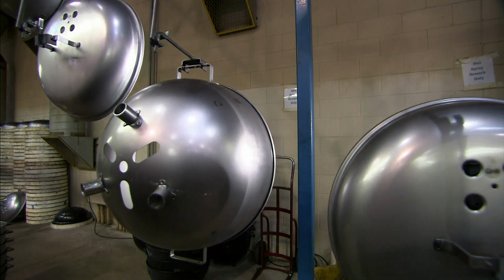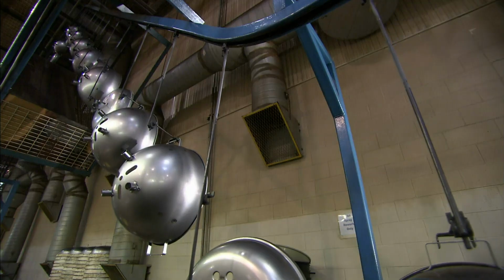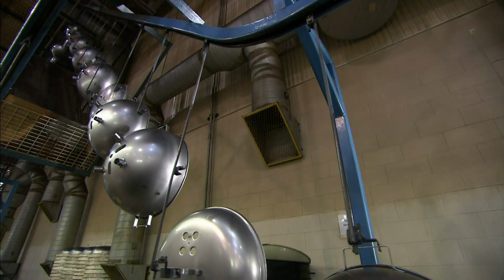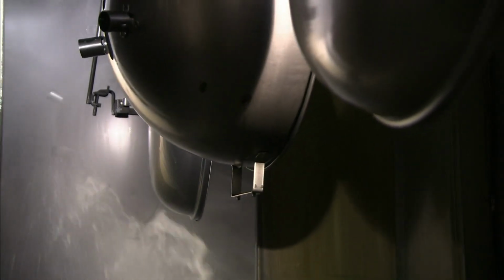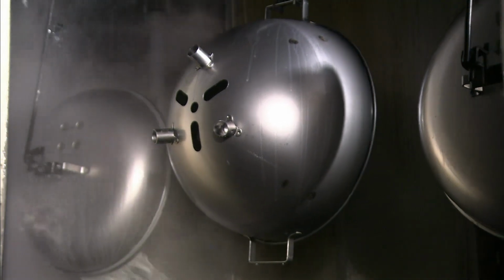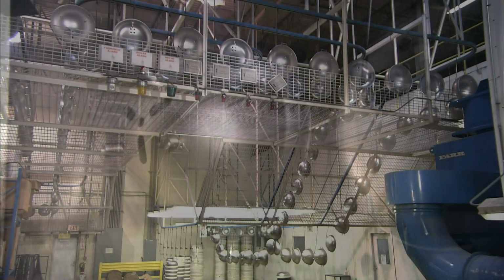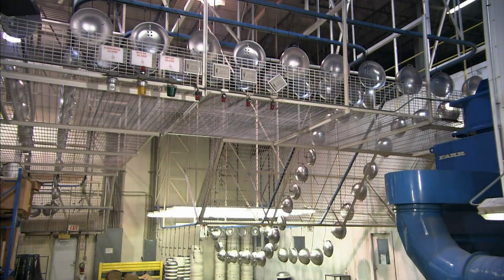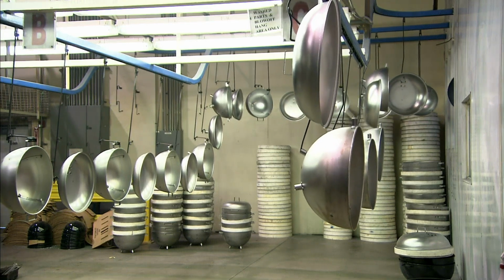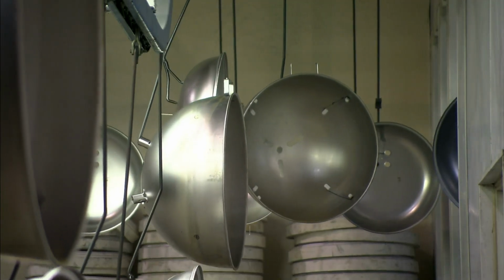The barbecue parts now travel on an overhead rail to the wash station. They're hosed down with soapy water, then rinsed clean. Once they're dry, it's off to the finishing department. Here, the parts are dusted with a glass powder. Then it's into a red-hot furnace set to 1500 degrees. The furnace bakes the glass dust into an enamel finish that protects the barbecue from rust and stains, so they'll last for years.